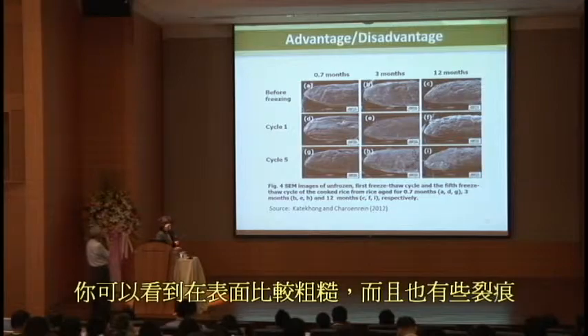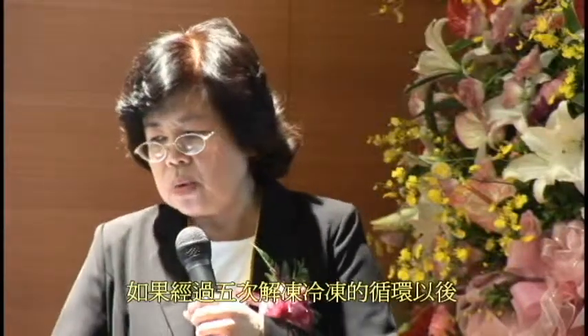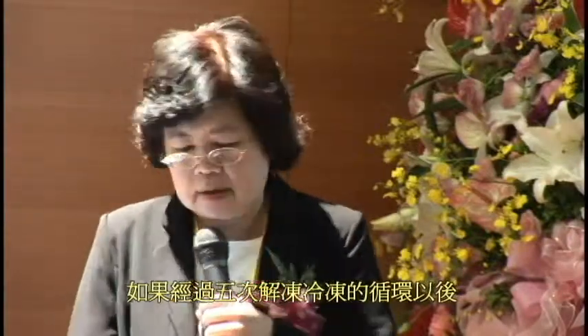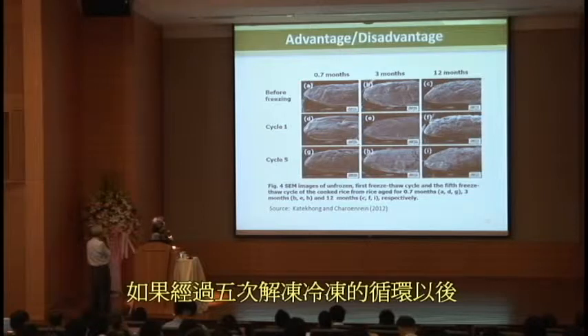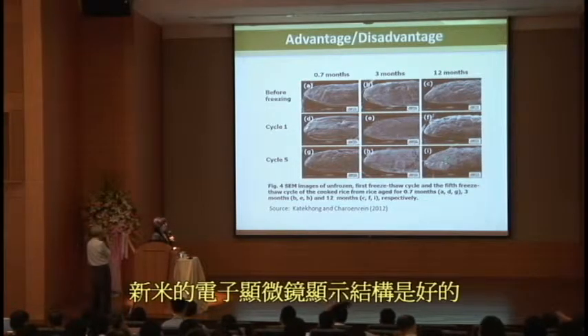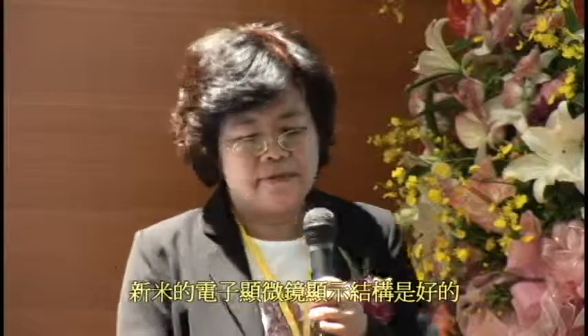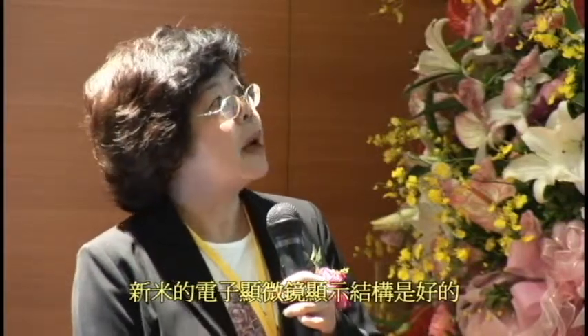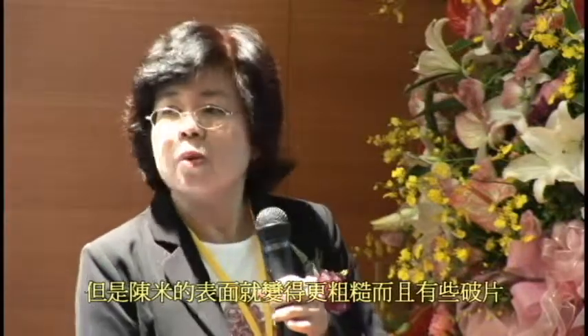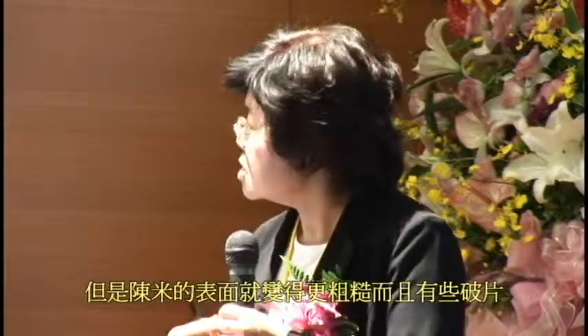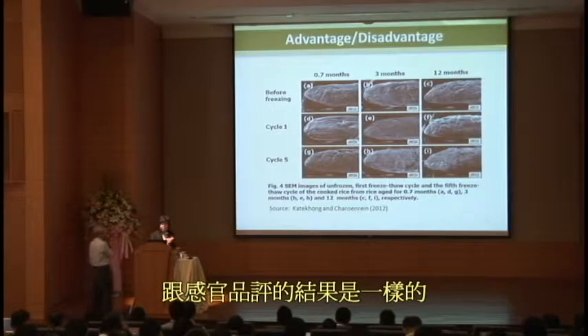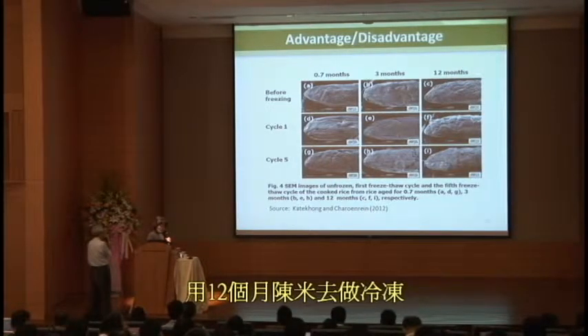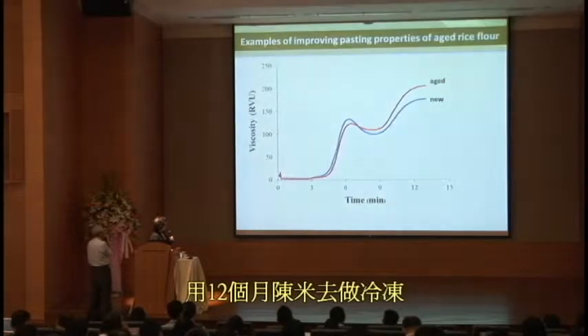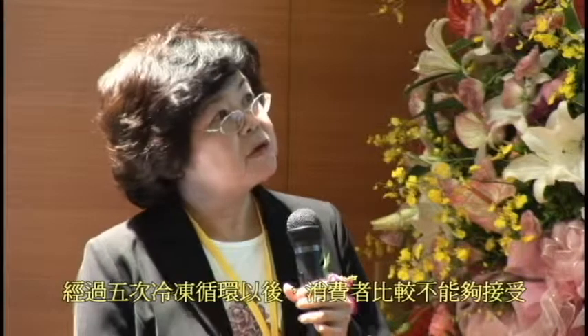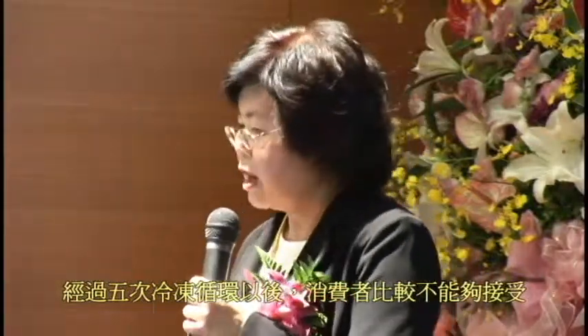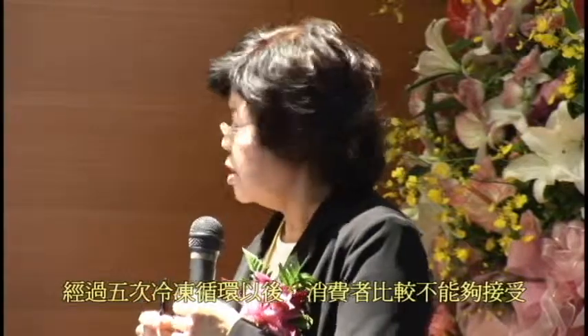So it's like cooked rice. And after we subjected this cooked rice to freezing and thawing, this is the first cycle, and then the fifth cycle. In the fifth cycle, you can see that the rice aged 12 months changed a lot. The surface is very rough and has some pores, while the microstructure of the new rice is still okay. This result also correlates with the texture, which shows that the cooked rice from 12 months, after 5 freeze-thaw cycles, still has a harder texture and less consumer preference.